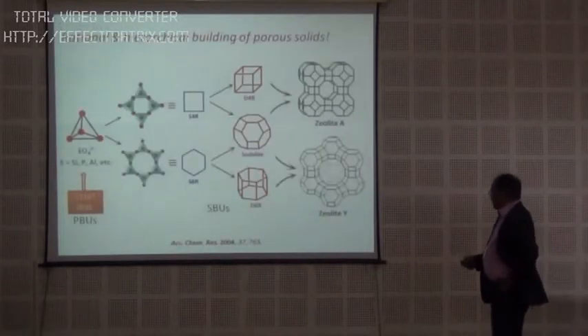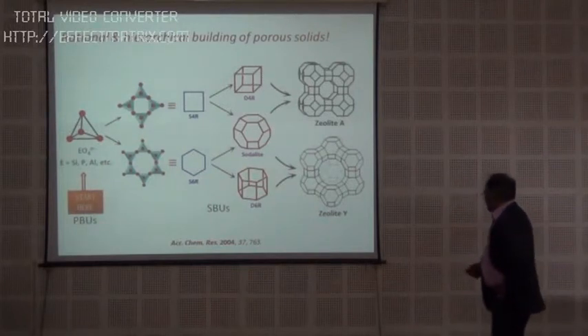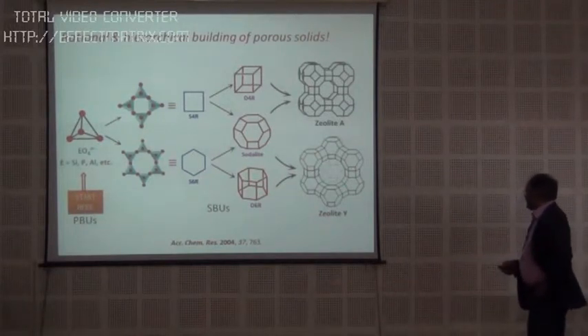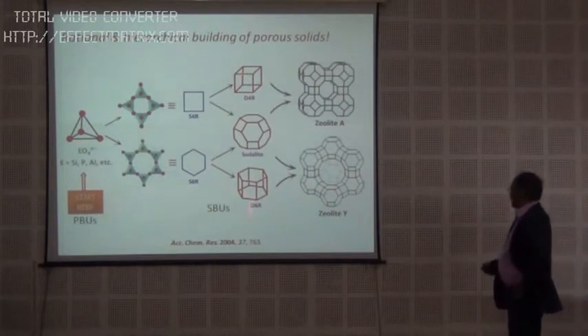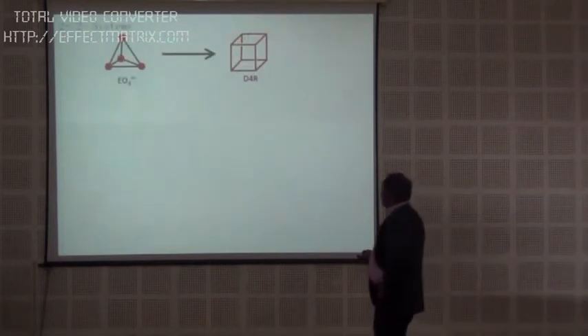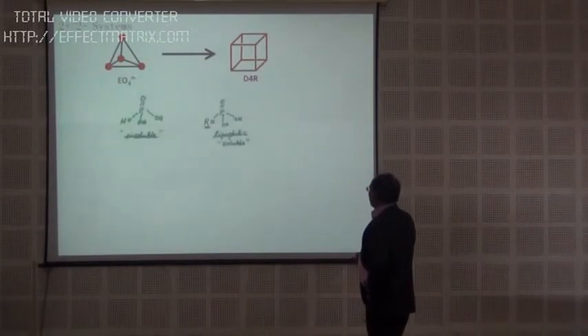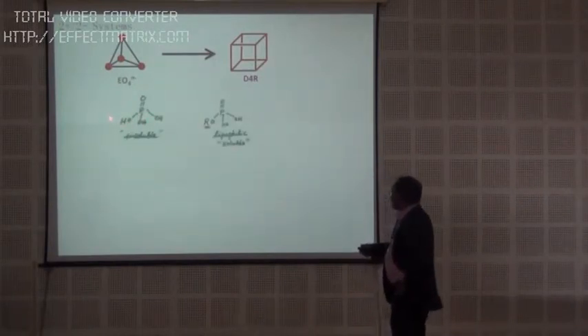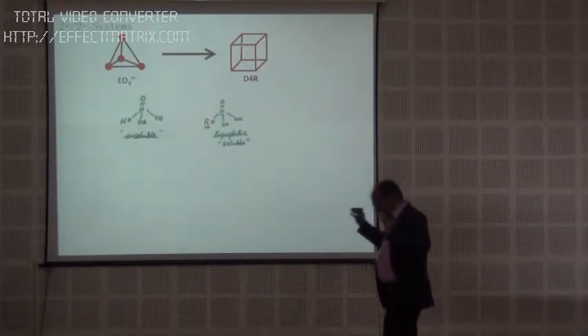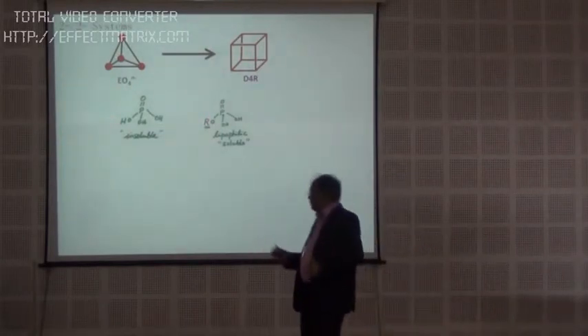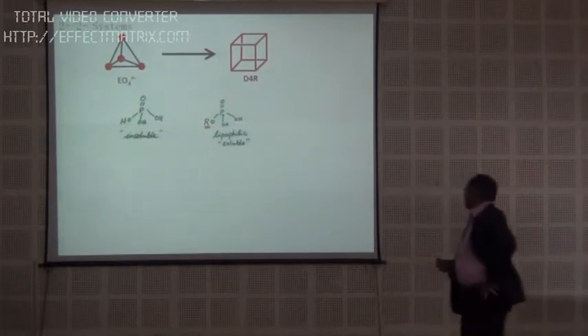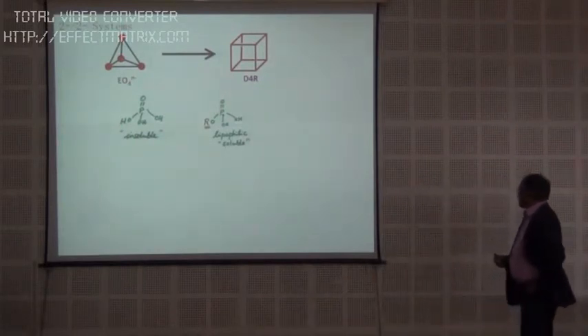In fact, we wrote this scheme in an article when we concluded the work on the ceramic materials, that one can extend this chemistry to porous solids, and we showed this cartoon about 15 years ago. And soon later, we did a small adjustment. This I already spoke about. If I compromise only one of the acidic protons with an R group, the R group should be large enough. It should impart enough solubility to the system so that I can do reactions in organic medium rather than in water at high temperature.